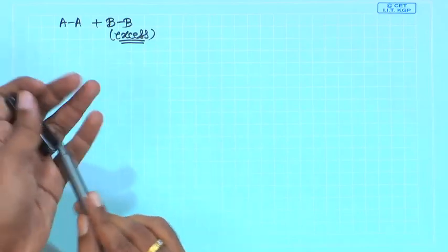Now, remember this term slight that I told, if you take one of the monomers in large excess, then what will happen is that before the polymer could develop into a substantially long chain, already both sides that majority monomer will react and those functions will be there. So, if you take diamine in a very large excess with respect to the dicarboxylic acid, all the dicarboxylic acid will react before a long chain has been produced, and then at the end the diamine will react on both sides and that will stop. That will be an oligomer at best.